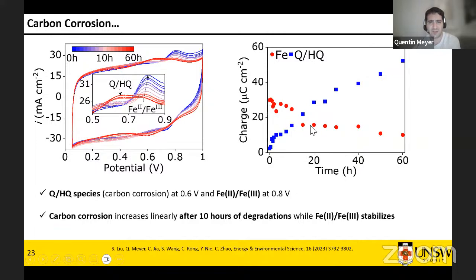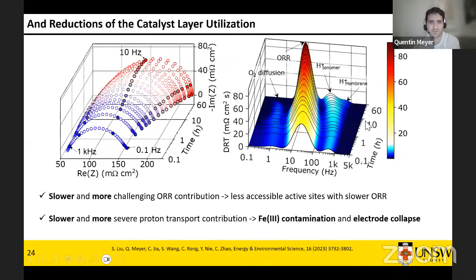We get a very quick loss of our iron and an increase of this functional group, quinone, hydroquinone, which are linked with carbon corrosion. So they're carbon-oxygen groups that form as carbon corrodes. So what we can see is that we have a lot of loss of iron. And then after 10 hours of operation, the cell basically just slowly corrodes in a nearly linear manner as we no longer seem to lose a lot of iron.